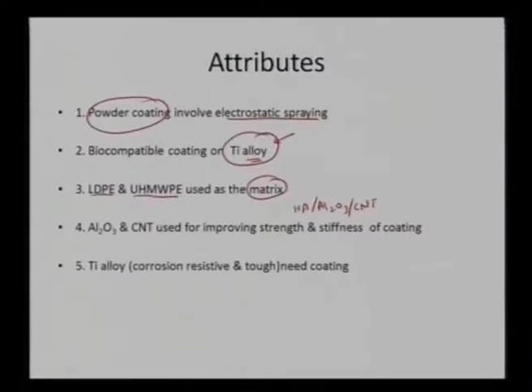And again, the metallic substrate is much better because of its superior corrosion resistance as well as its toughness. So once we select a very appropriate biomaterial, we can always apply a coating of polyethylene, which is still a biocompatible material, and we can enhance its strength by using certain reinforcements such as hydroxyapatite, alumina, or carbon nanotube. And again, their incorporation will vary depending on what kind of applications we are aiming at.